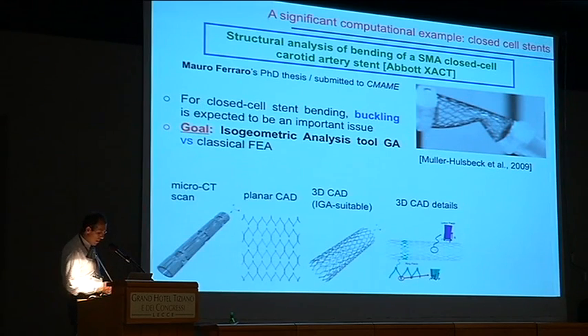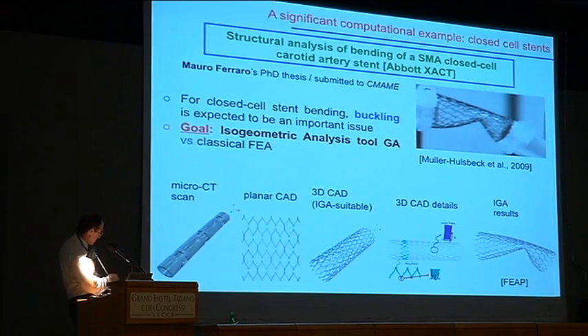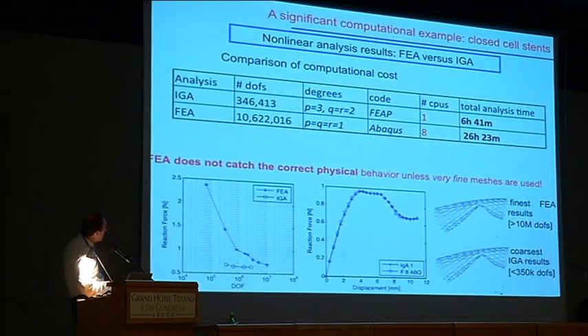And so we start from a micro CT scan of the real geometry. We develop a finite element mesh and an IGA mesh, and we run the simulations. And as you can see, from our numerical scheme we can qualitatively very well reproduce the experimental results. But again, this was in some sense a seminal work, because the more we work on this area, the more problems we face and the more interesting things we found. And here is something I would like to share with you, which was kind of astonishing.